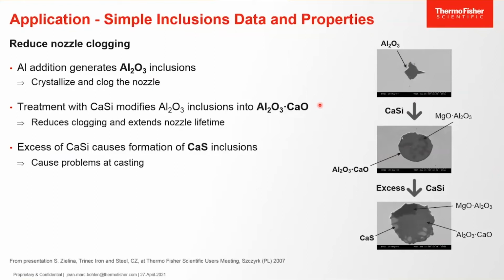When you do that, the consequence is that you reduce the risk of clogging and extend the nozzle lifetime. You have here an example of an inclusion that is modified from aluminum oxide to calcium aluminate. Now, when steelmakers put calcium additive in excess, there might be the formation of calcium sulfide inclusions. That are also problematic because they cause problems at the casting.